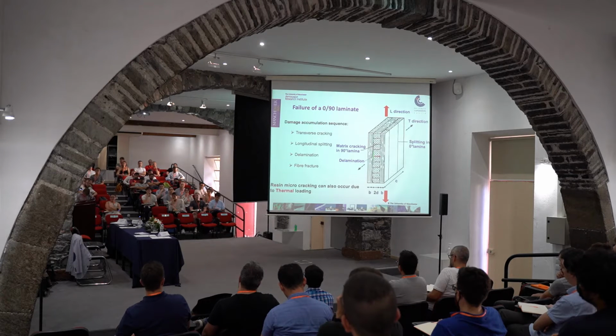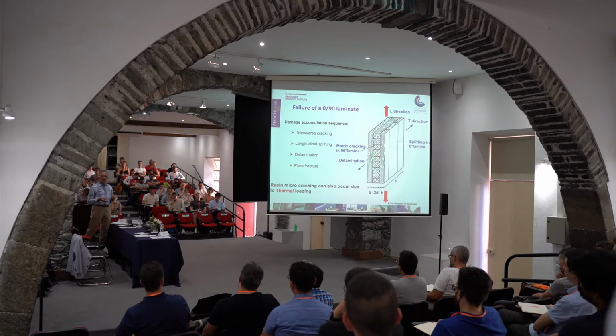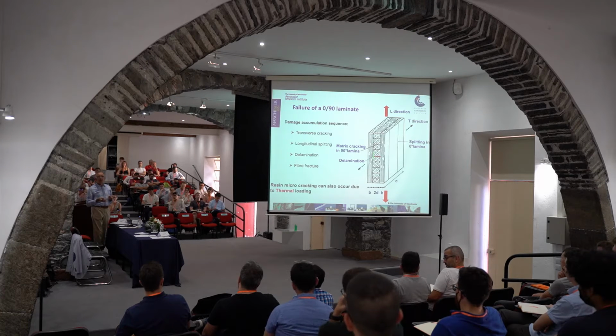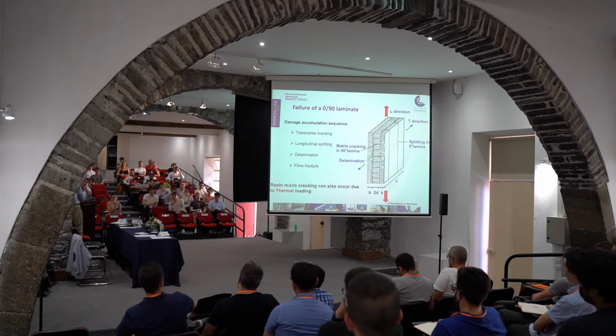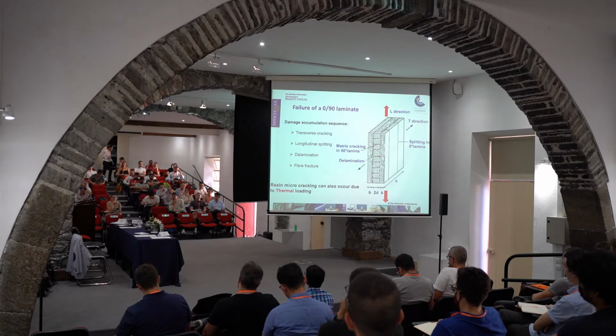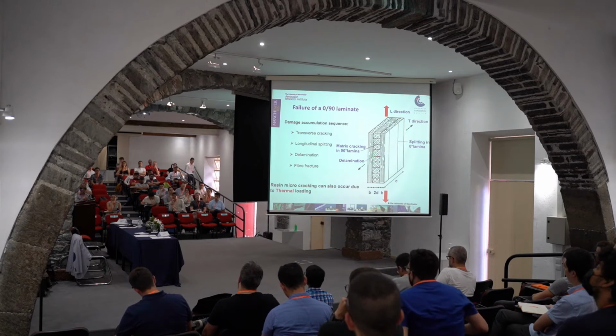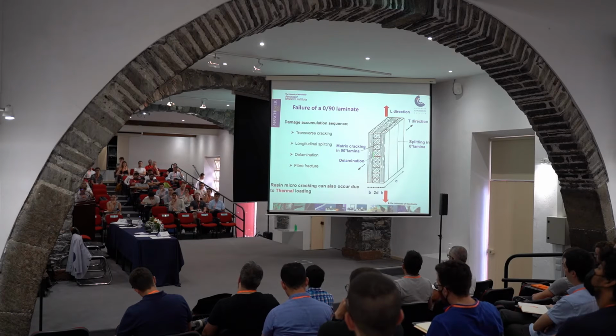Usually we use epoxy resins. They usually crack at about 5,000 microstrains. What's 5,000 microstrains in percent strain? 5,000 microstrains is 0.5%. Yeah, so it's relatively low. And then, of course, the task we have is how to design resin systems that will crack, but at much higher strain.